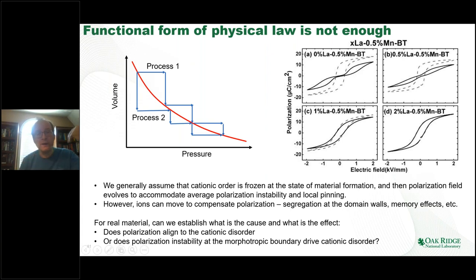But I also know that ions can move to compensate polarization. So there are things like segregation at the domain walls, memory effects, and so on. So in the real material, I don't know whether the polarization aligns to the frozen cationic disorder, or whether the polarization instability drives the cationic disorder. And knowing this is actually pretty important because it affects my strategy for designing materials with interesting properties.